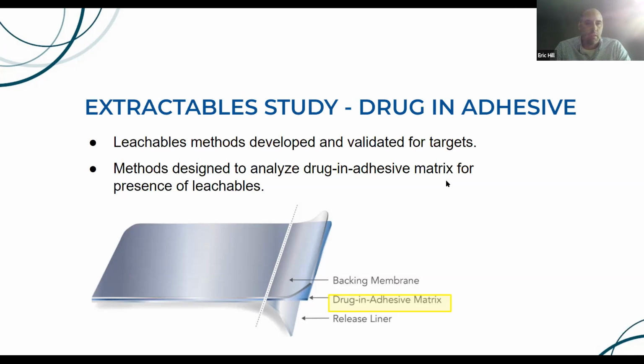So you can imagine that presents a very tough challenge, analyzing an adhesive matrix, which is usually going to have a polymer involved, to specifically look for leachables that have come from the backing membrane, the release liner potentially, the pouch that it's packaged in, or they could even be leachables that come from interactions between those materials and the adhesive. And so we certainly have a challenge in front of us.